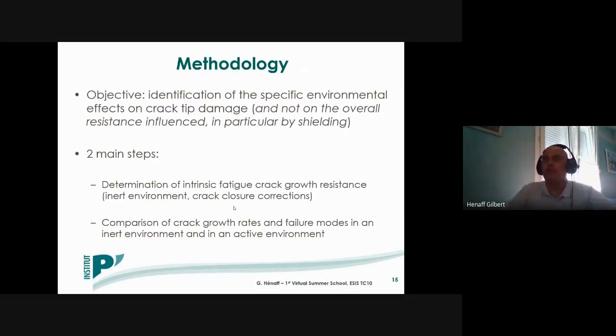So from all these examples, we can deduce some methodological aspects. Our objective in the following will be to try to identify the specific environmental effect on the crack tip damage and not on the overall fatigue crack growth resistance, in particular by taking into account the shielding induced by crack closure effects.